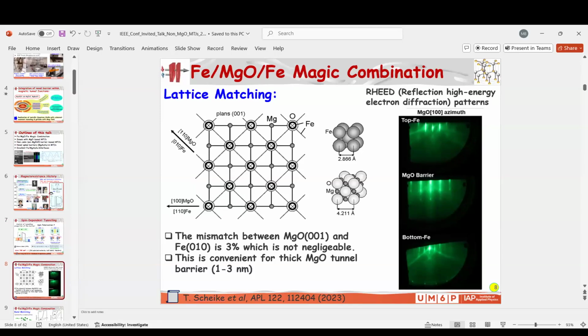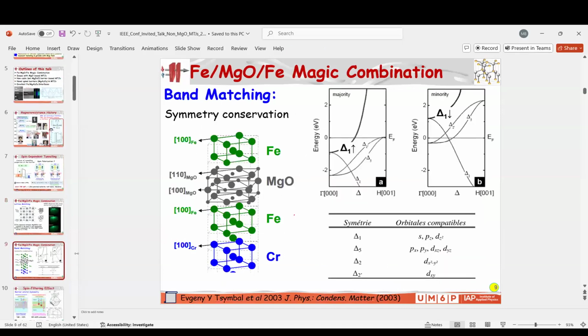Also, we are limited with the usage of the thickness around 1 to 3 nano. So below 1 nano, things start to become difficult. Also, we have the spin filtering. This is also one of the good aspects of this magic combination, the spin filtering, because of the iron.